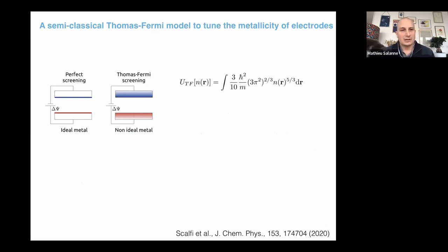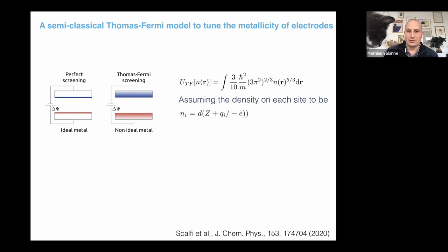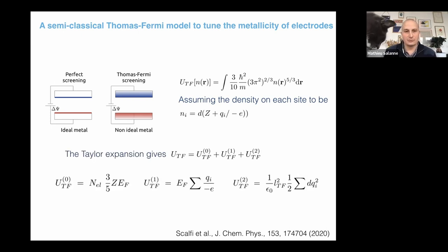Recently, we saw that for systems like carbon, it is not a good idea to treat them as perfect metals, because you can have some screening and they are not good metals, in fact. And so, based on a proposition by Lydéric Bocquet, we started to implement a Thomas-Fermi model. The idea is that the Thomas-Fermi functional accounts for the kinetic energy of the electrons. So what we did is to assume that the charge perturbation on each site, on each atom, is small compared to the total electron density at this position. And so this allows you to do a Taylor expansion. And the terms are quite easy to derive.